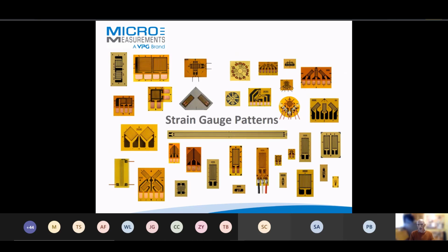Now this strain gauge is a photo etch device. So we take a foil, bond it to a carrier, and then we photo etch a pattern. So they can be photo etched in many different patterns. Now I've been saying for 30 years that we do 250,000 different types of strain gauge, and we produce new, custom patterns every week. So it's certainly well over now 250,000 different patterns. We can have what's called a single linear strain gauge, designed to measure strain in one direction. We can measure torsion or shear, so you might want to convert a drive shaft to torsion measurement for power